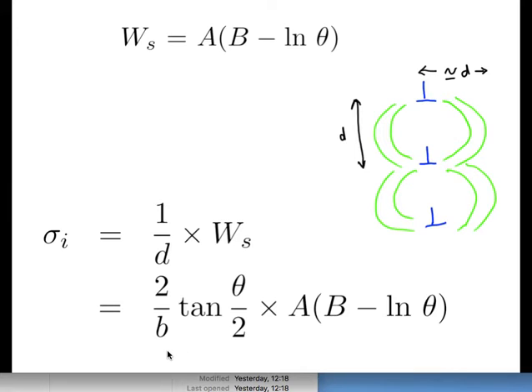So that's quite a powerful result, starting by the fact that we can accommodate the misfit between two crystals, in other words, the gap that is left when I tilt the two crystals, by shoving in edge dislocations. And a second physical principle, that when we have an array of dislocations, the strain field only extends approximately to the distance given by the separation of the dislocations, okay? Not all the way to the size of the crystal. It's easy to work out the interfacial energy per unit area as the number of dislocations in a unit area of interface multiplied by the energy per unit length of those dislocations. Everyone happy with that?